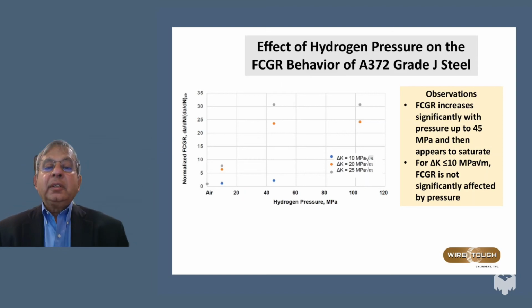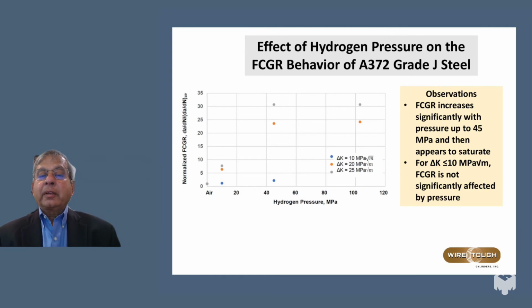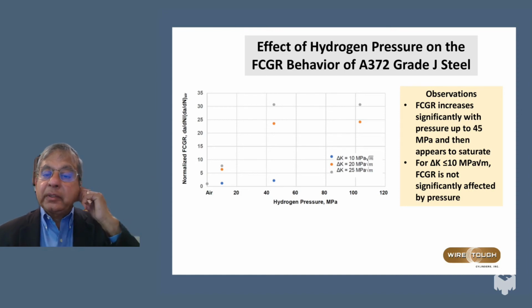Now, hydrogen pressure is another variable that can affect the fatigue crack growth rate, and it is important to document the effect of pressure on the fatigue crack growth behavior. And here it is. You can see at delta K of 10, 20, and 25, the fatigue crack growth behavior at different values of hydrogen pressure. We observe that the fatigue crack growth rate increases significantly with pressure up to 45 MPa and then appears to saturate. For delta K less than 10 MPa root meters, fatigue crack growth rate is not significantly affected by pressure.